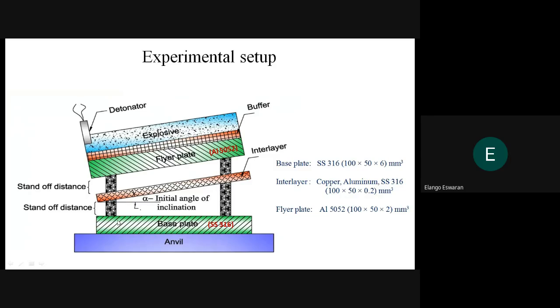The distance between the flyer and the interlayer, and the interlayer and the base plate, is varied from 6 mm to 10 mm, which allows the flyer plate to reach its terminal velocity. Similarly, the inclination angle, that is the angle between the flyer plate and the base plate, is varied as 6 degree, 8 degree, and 10 degree respectively. A buffer plate is placed above the flyer plate to protect the flyer plate from damage during the explosive process. The explosive was packed above the buffer plate, and the detonator was placed at one corner of the explosive pack.